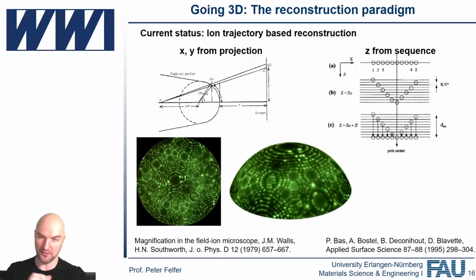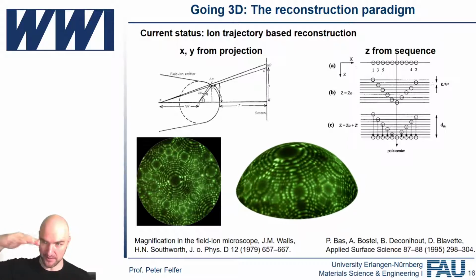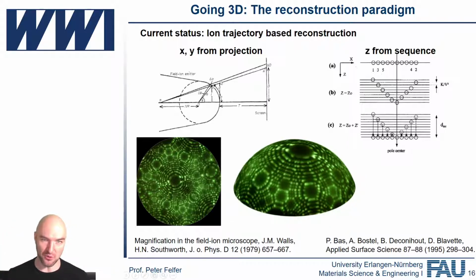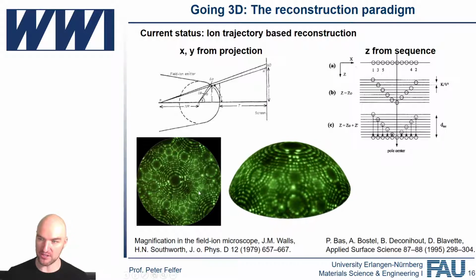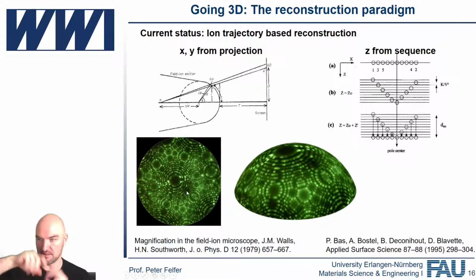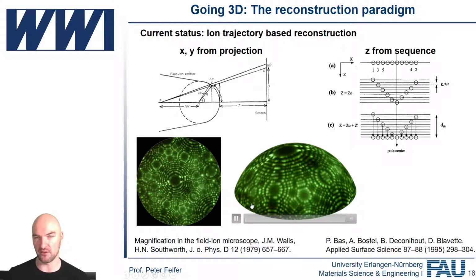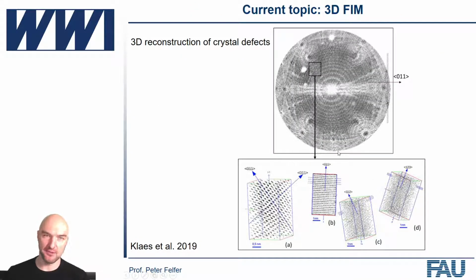The one thing we've obviously added is, as we evaporate the sample, the reference plane, if you will, of where that image is happening moves through your sample. So this is the tomographic aspect of everything. We say, okay, we've removed X volume from our sample. So the plane where this image sits, where we allocate this image, moves into the Z direction. But we're going to talk about that in detail tomorrow. And you can actually use that also for field ion microscopy and do 3D reconstructions.